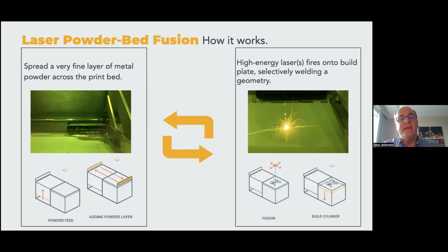Again, as you can see in the left-hand photograph and the figures on the bottom, we have the powder feed cylinder, which is being lowered. The recoater, you can see in the green photograph there, it's on the right-hand side. That is what spreads the powder onto the build cylinder. And then in the right-hand photograph and figure, you can see the high energy laser being active. And in this case, tracing out the name of a product called XM200G. And again, repeated over and over and over again. The beauty about this technology is that as printed, the part has over 99.5% relative density.